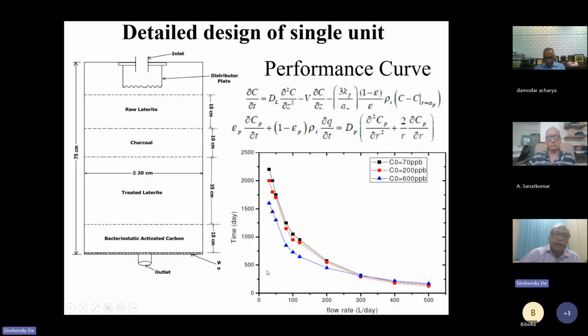In this performance curve, the y-axis is time, that means the life of the filter. On the x-axis we have the flow rate, for different feed concentrations of arsenic. So if you have an arsenic concentration of 70 ppb, 70 microgram per liter, and a flow rate of 100 liters per day, then the life of the filter will be around 1200 days. That is close to 4 years. So one can really design a particular filter and predict the lifetime of the filter. Since its capacity is high, during its lifetime one need not go for chemically induced regeneration.